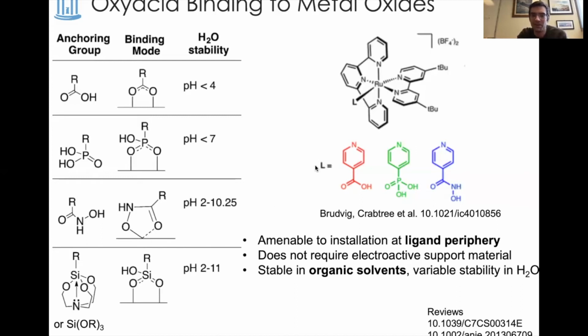An advantage of this, or one of the key reasons to choose an attachment like this, is that it's quite amenable to peripheral attachment on your ligand. So this ruthenium complex shown here shows a pyridine ligand where the para position can either have a carboxylic acid or a phosphonic acid or a hydroxamic acid. And that means that when you link the complex to the surface, the linkage is far away from the metal. So you're not going to perturb the d orbital energies or the metal ligand binding as much as if you have a direct metal to metal oxide linkage as in the prior slide.